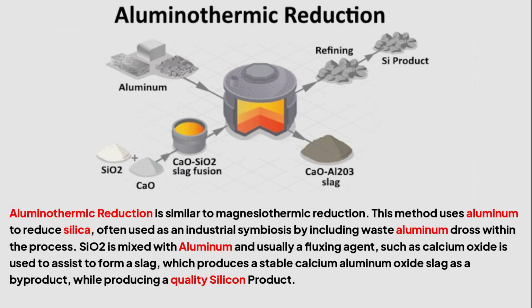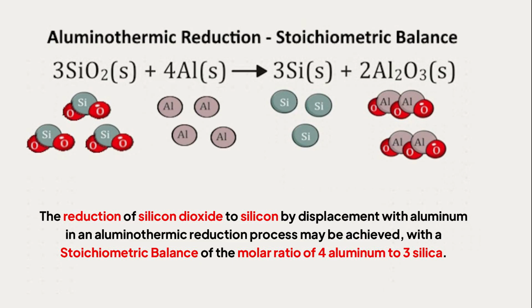Aluminothermic reduction is similar to magnesiothermic reduction. This method uses aluminum to reduce silica, often used as an industrial symbiosis by including waste aluminum dross within the process. SiO2 is mixed with aluminum and usually a fluxing agent, such as calcium oxide is used to assist to form a slag, which produces a stable calcium aluminum oxide slag as a byproduct, while producing a quality silicon product. The reduction of silicon dioxide to silicon by displacement with aluminum in an aluminothermic reduction process may be achieved, with a stoichiometric balance of the molar ratio of 4 aluminum to 3 silica.